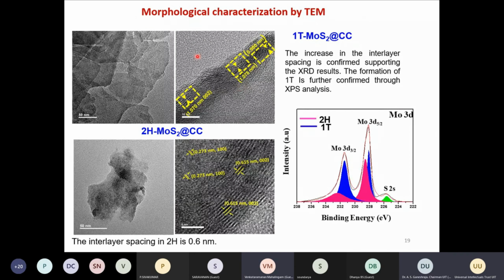Okay, so you can actually do a TEM analysis to find out the layer distance, which I was talking about. The increase in the layer distance is confirmed by high resolution transmission electron microscopy, where you can see an increase in the distance from 0.65 to almost 1.07 nanometer. So there is an increase in the layer distance upon incorporating this ionic liquid inside the material.